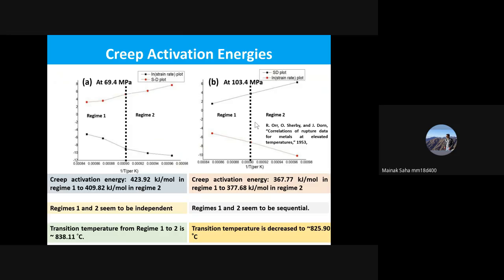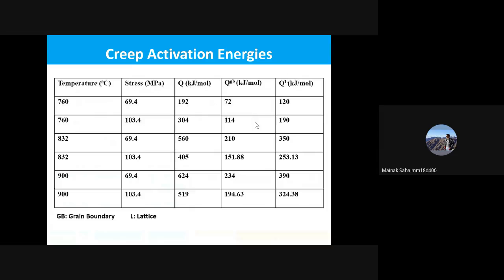So with this approach, now at different stress levels, 69.4 and so on, and all these temperatures, 760, 832, 900 degrees, all have been taken from the work of Hayes and Martin, wherein mathematically the activation energy has been found as follows. That's what we can observe. This is the creep activation energy, and these are the components of the creep activation energy. QGB is the creep activation energy at the grain boundary, and QL is the creep activation energy for the lattice, as you can see very clearly.